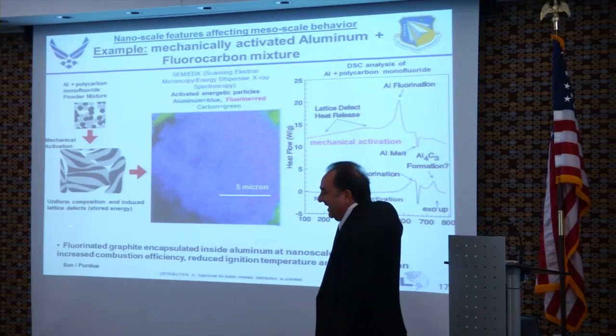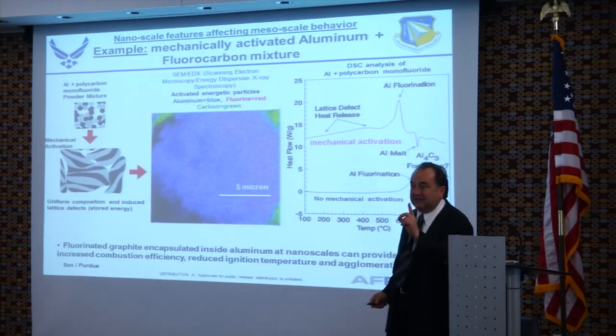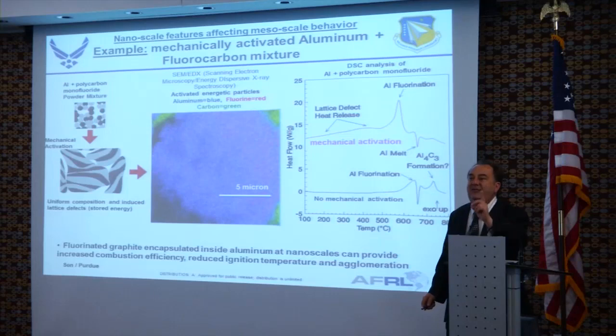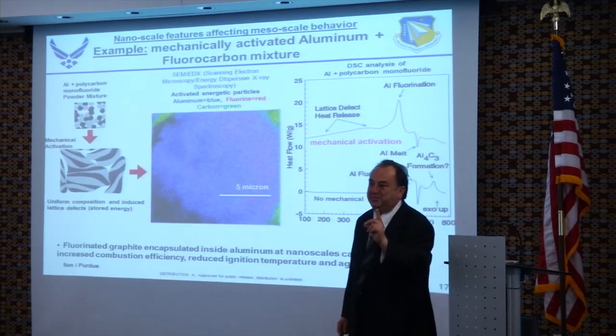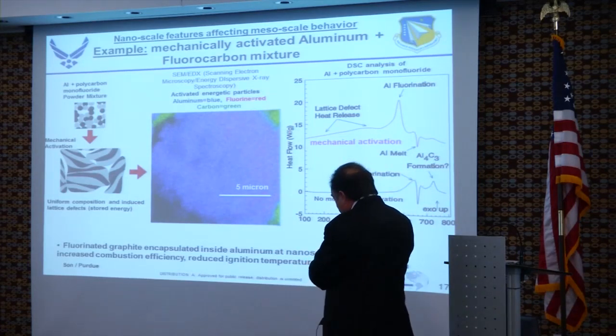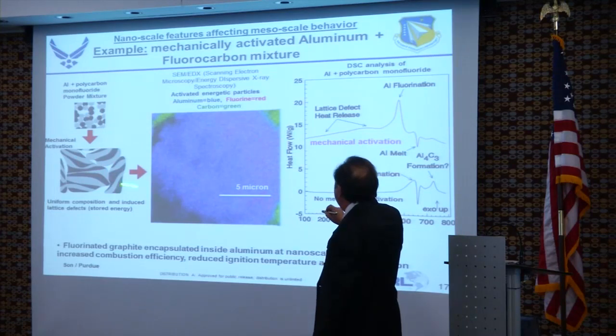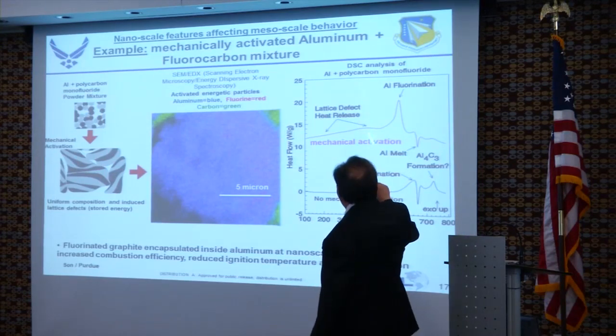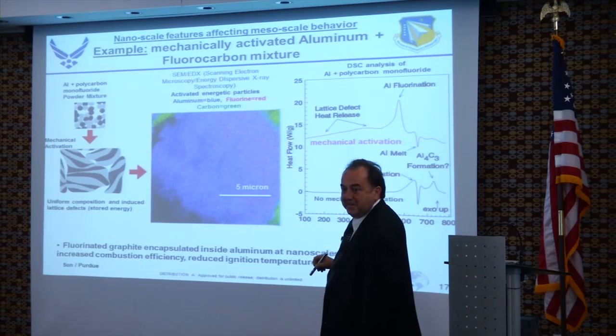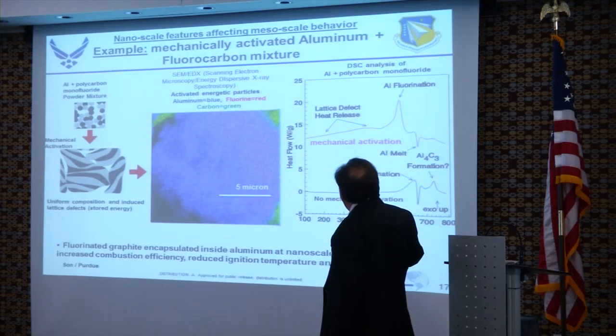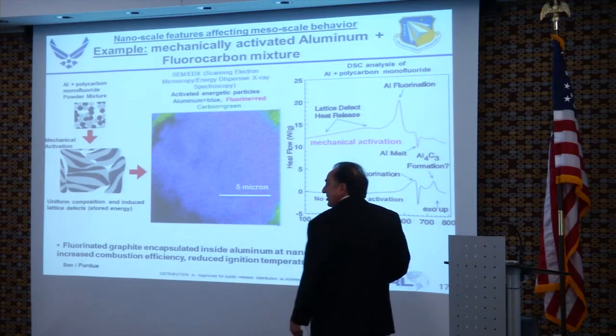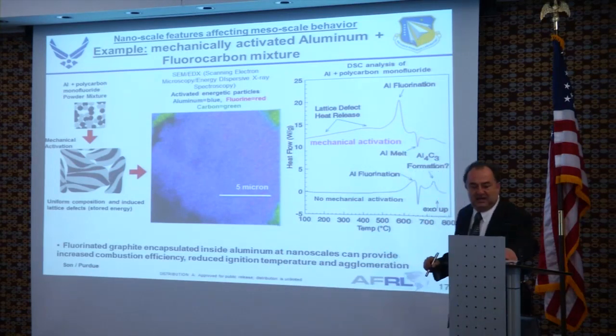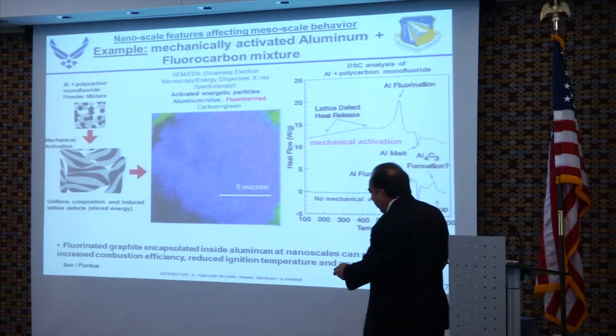those lattice defects, again, are a material problem. Lattice defects store energy. And they were surprised to find out that energy actually increases the heat value, doubles it up. Then you can reduce the ignition temperature to around 350 degrees Celsius. Now, the third example is about